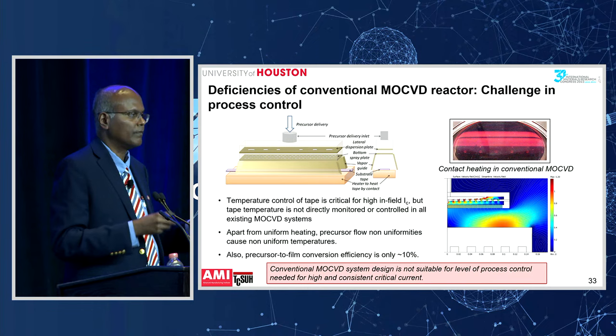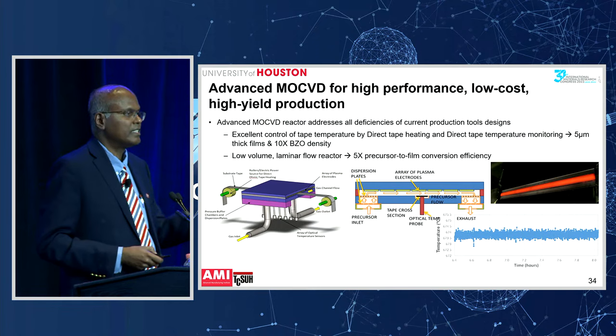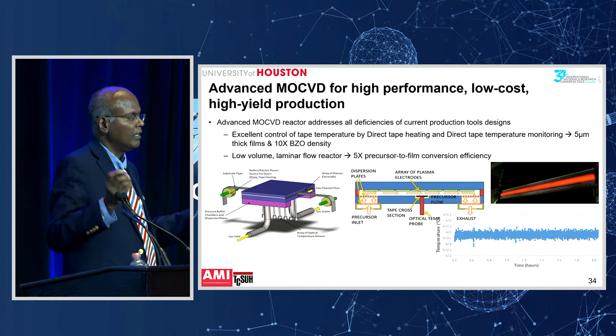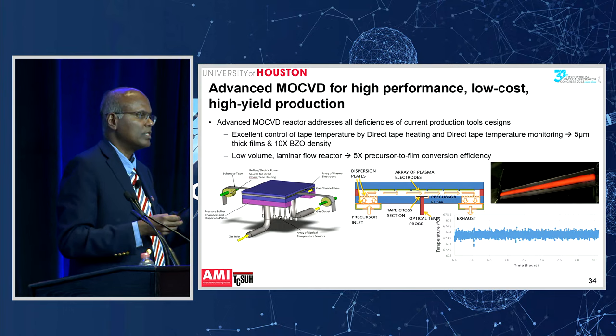So we came up with a different technology called advanced MOCVD. What we did was we threw out the heater. We threw out the showerhead, right? So without heating externally, what happened was, the substrate that we use is Hastelloy, a nickel alloy, it's a very resistive material.